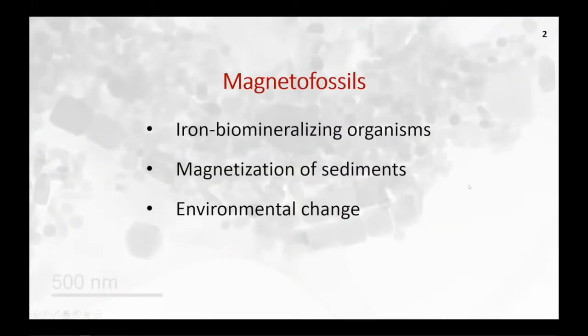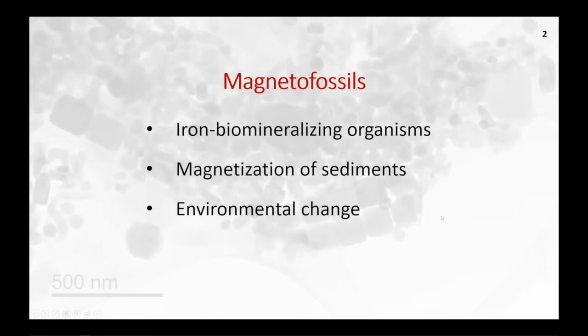What are magnetofossils and why are they important? They are the remains of iron biomineralizing organisms, including magnetotactic bacteria. Due to the stable single-domain nature of most magnetofossils, they can contribute a large proportion to the natural remnant magnetization of sediment. Because of the environmental sensitivity of magnetotactic organisms, magnetofossils can be used to study environmental change.